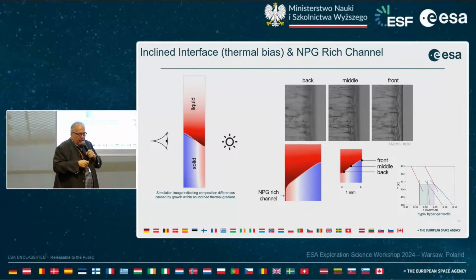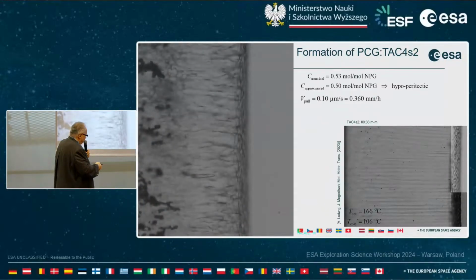So this sounds bad, but on the other hand, we found out that if we have a perfect sample, we see nothing of the dynamics, because then we are looking at a plane surface at a right angle. So now, okay, let me see how it works, as the technician said. Yeah, okay. Here you can see the typical solidification experiments in space.